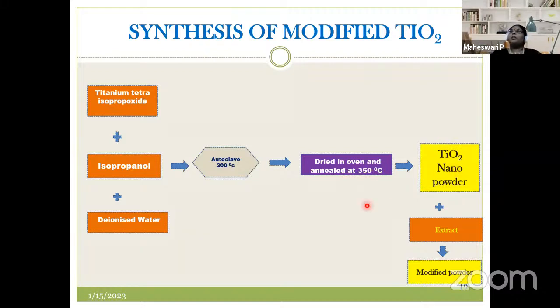Now we have taken aqua rosa. It's a normal, we call it paneer roses, okay? So that aqua rosa, we have taken and made into an extract. That extract was mixed with this nano powder using a magnetic stirrer. We stirred for several hours, then we centrifuged and dried it, and made it into a powder. That powder comes under the category of aqua rosa modified titanium dioxide nanopowder.